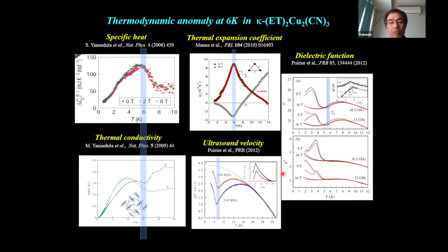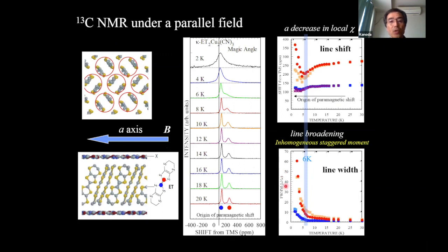Let's take a look at the magnetic properties around 6 Kelvin. This is the carbon-13 NMR spectra. In these experiments, we apply the magnetic field along the layers. In this field configuration, we have two NMR lines. Each comes from each of the two carbon isotope sites within the molecules. And at lower temperatures, the line shape changes. The important point is that below, say, 6 Kelvin, the two-peak structure is gone. This is due to the spin susceptibility decrease.